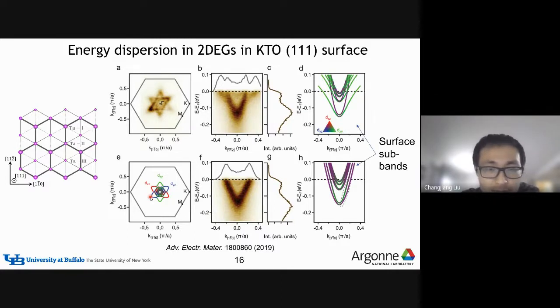Just before showing you the measurement at lower temperature, I would like to mention that previously, people have found, using ARPES, which is the angle-resolved photoemission measurement, which can probe the electronic structure, that on the KTO 111 surface, the electronic structure forms a star-shaped or honeycomb-shaped structure with six-fold symmetry. This six-fold symmetry is a direct result of the honeycomb-shaped crystal structure, and this behavior is consistent with the theoretical calculation shown below. Besides this six-fold symmetric electronic structure, people found that at the interface there are some surface subbands forming, which is due to quantum confinement, and this quantum confinement is responsible for the two-dimensional electron gas.